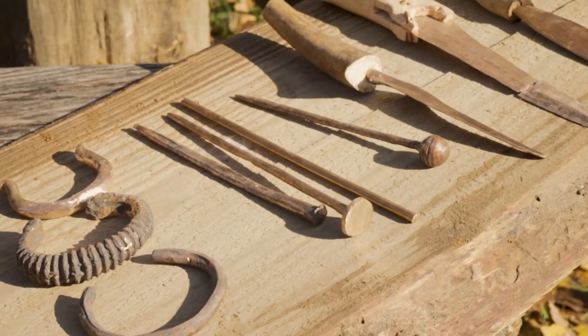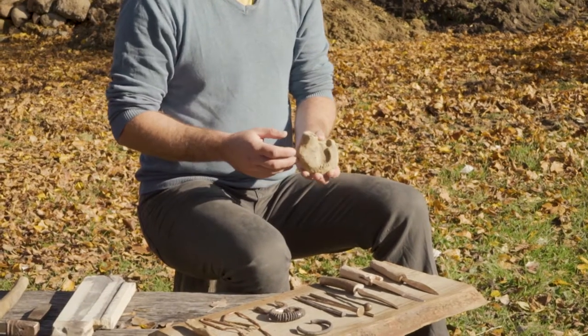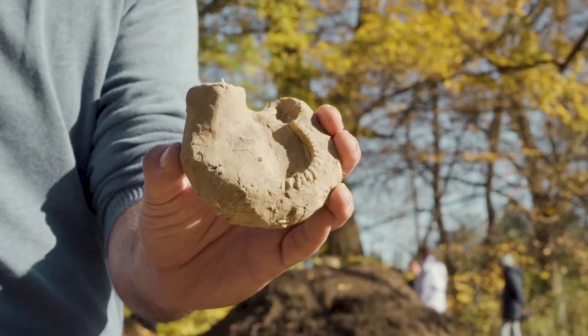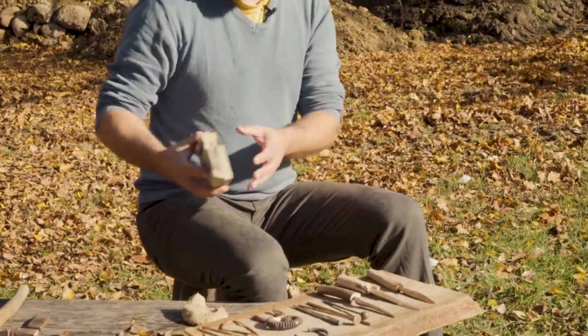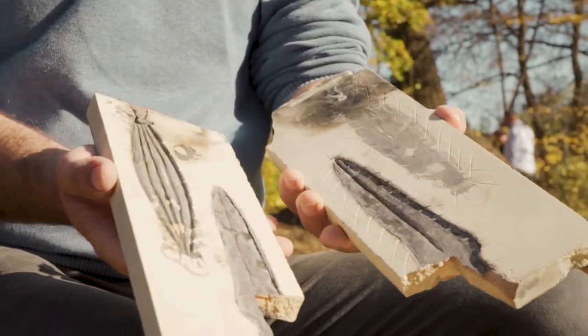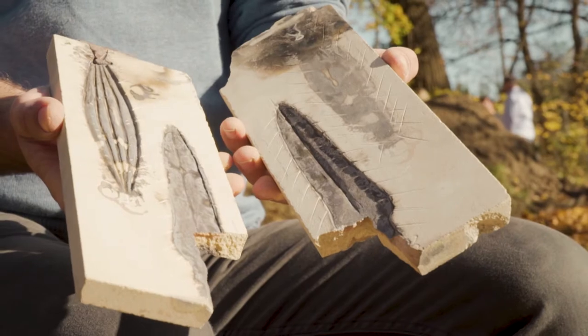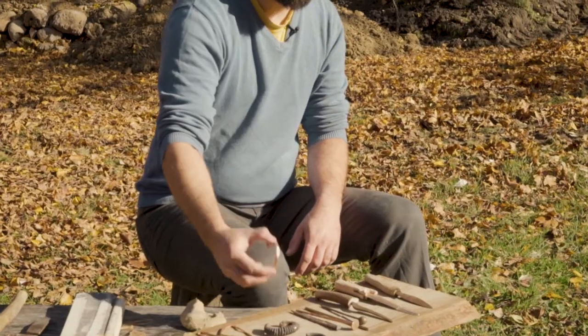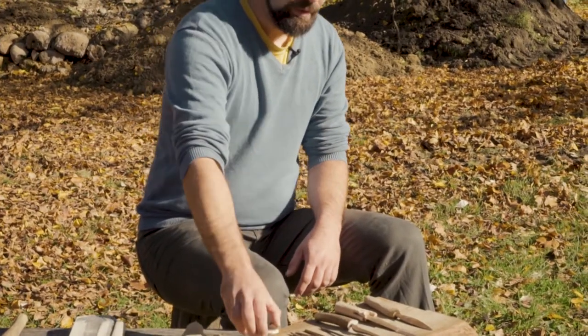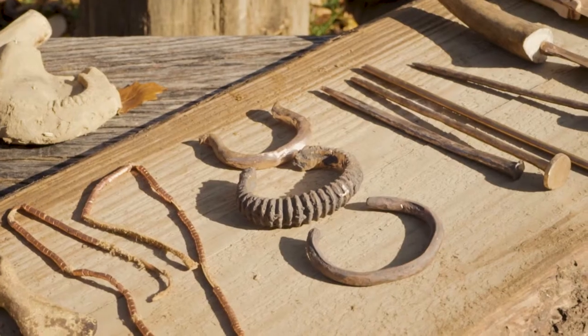The objects were made using two different processes: firstly in lost molds, where the pieces were cast in clay, or secondly in two-shell sandstone molds, such as this one, in the shape of a dagger. They were then reworked in different ways. This ribbed bracelet was left as an unfinished casting. This bracelet has already been completely polished, while this one is still covered with annealing scale from intermediate annealing during the forging process.